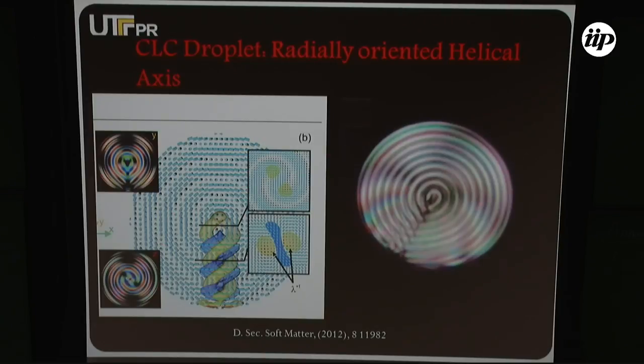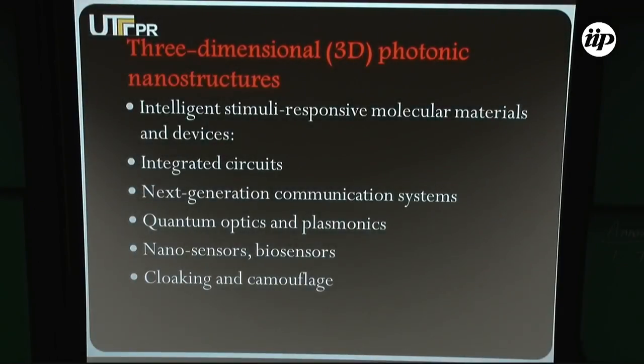This is a planar-oriented droplet, and what happens here is you have this kind of double twist orientation, and you get a point defect at the surface, a boojum. People thought before that you would have defect lines here, and they just showed in this paper that all you have are non-singular lines running here. But there's still some debate about this.